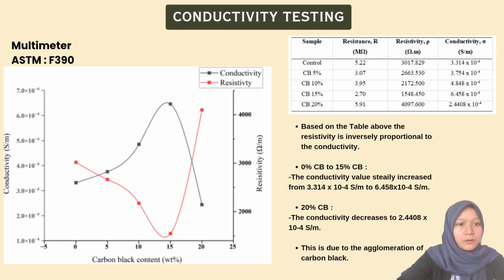For the conductivity testing of multimeter, it can be seen based on the graph. The resistivity is inversely proportional to the conductivity. For 0% of carbon black to 15% of carbon black, the conductivity value increased steadily from 3.314 times 10 to the power of negative 4 Siemens per meter to 6.458 times 10 to the power of negative 4 Siemens per meter. For 20% of carbon black, the conductivity decreased to 2.4408 times 10 to the power of negative 4 Siemens per meter. This is due to the agglomeration of carbon black at 20% of CB.